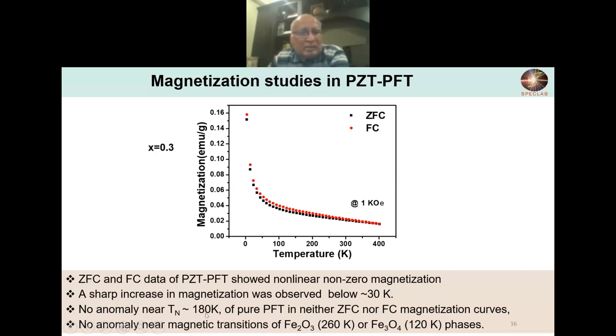So the interesting thing is that in these materials, if it were phase separated, then PFT and PFN have a Néel temperature, Tn, around 180 degrees. You see nothing around 180 degrees here. That shows that the material PFN or PFT has made a real solid solution with PZT, and they have lost the properties of the individual PFT or PFN. Because if the individual components were existing in our solution, we should be getting some kind of peak around Tn.